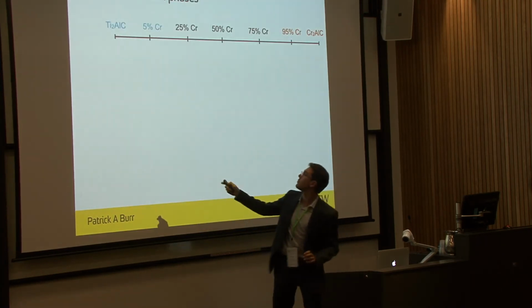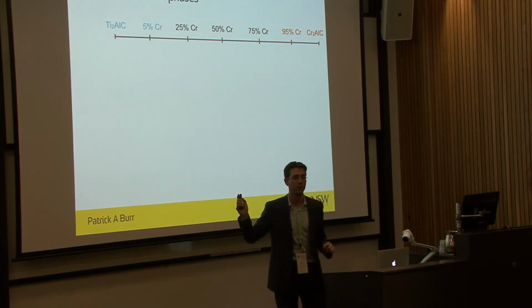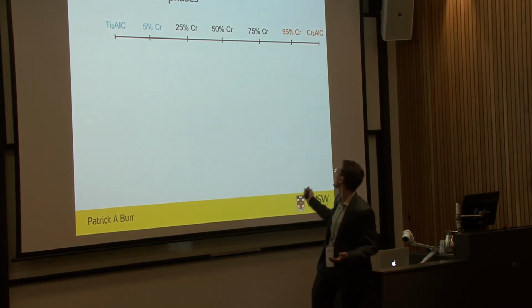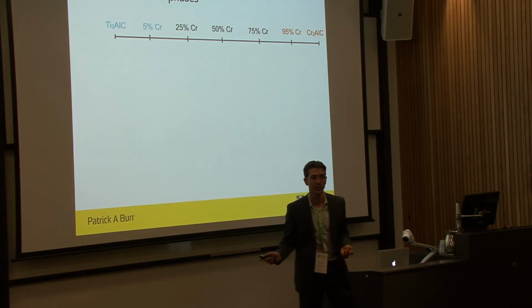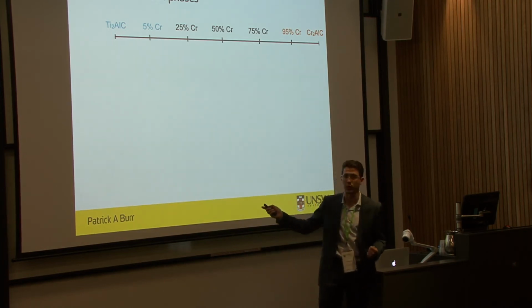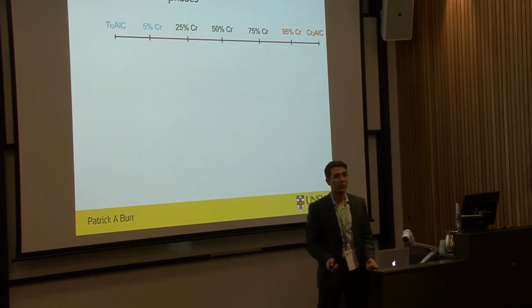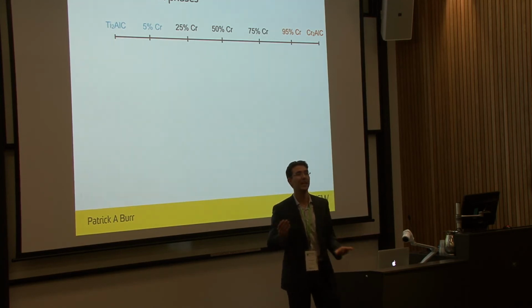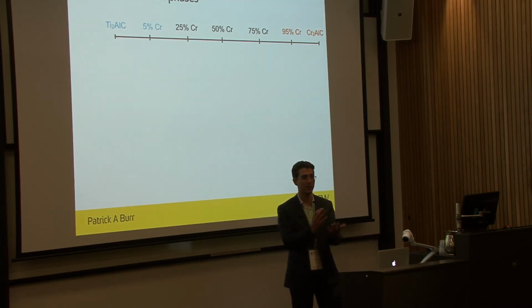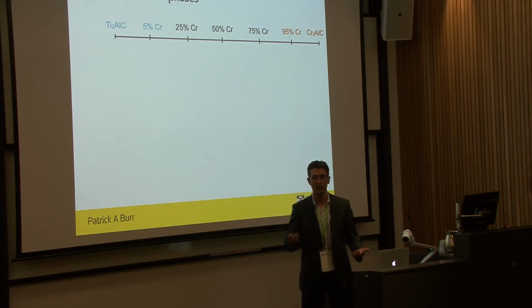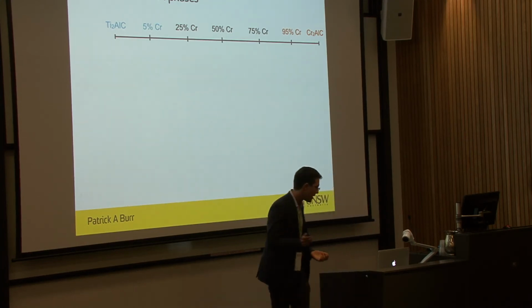In particular, titanium aluminum carbide sticks very well to zirconium cladding. Chromium aluminium carbide has excellent corrosion resistance. Our idea was, can we make something, can we tailor the properties, both of the lattice parameter to get it to stick to zirconium and the corrosion resistance, by making a mixture?